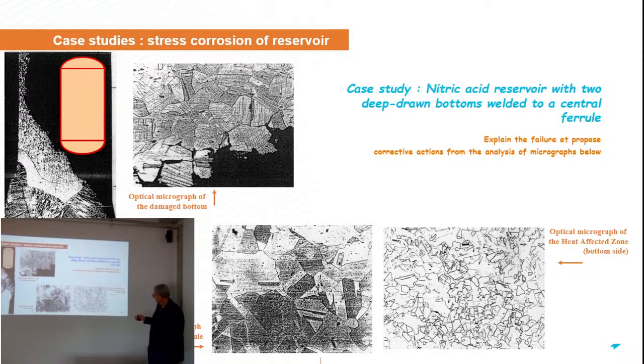And you can see here a very interesting image showing the heat affected zone of the bottom side. So this is somewhere here. And you can see here a very, very small metallurgical grain, indicating that the material has recrystallized in this part. You know that the welding here brought some high temperature in the vicinity of the weld, and because you have some deformation due to the deep drawing of the bottom, you can have recrystallization. You need temperature and critical deformation to be able to recrystallize. So this is another evidence of some residual stress in the material, in addition to the analysis of this image. So probably here we have a case of what we call stress corrosion, a combination of corrosion by nitric acid and some residual stress in the material.